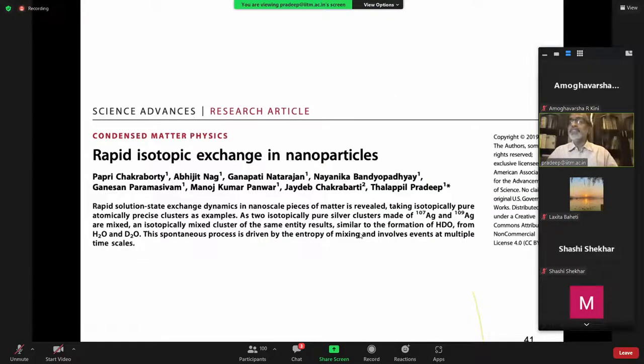Now, what is the best way to study this? Best way to study this is to take a silver cluster where you have an isotopically labeled silver. Let us say silver 109. And another cluster, which is silver 107. And if there is atom exchange happening, then by mixing these two clusters, immediately after mixing, you should see an isotopically mixed cluster. And this is what we saw in this rapid isotopic exchange.